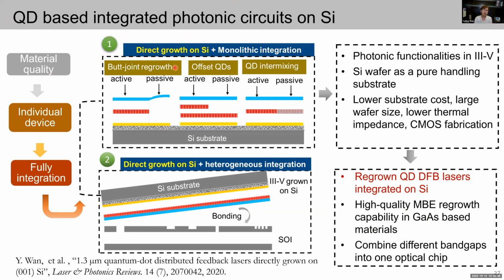So today, indium phosphide-based monolithic integration and silicon-based heterogeneous integration are the two most important on-chip integration technologies. And quantum dot-based photonic integrated circuits on silicon can thus be built upon what has been achieved through either monolithic or heterogeneous integration. So in the first platform, all the photonic functionalities are performed in the III-V materials, and the silicon wafer is only used as a handling substrate. So this approach benefits from the lower substrate cost, the larger wafer size, the lower thermal impedance of silicon, and the well-established wafer scale CMOS fabrication, and it can be achieved by regrowth, offset quantum dots, intermixing, etc.